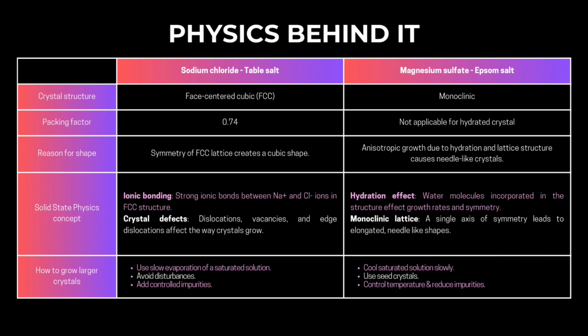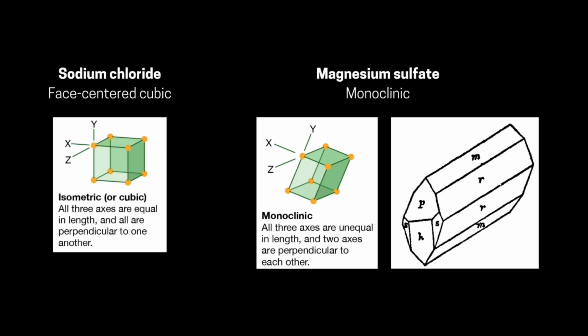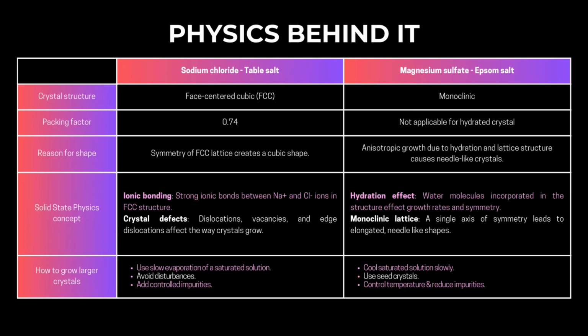Sodium chloride has a face-centered cubic crystal structure, and magnesium sulfate has a monoclinic crystal structure. This actually relates to the shape of the crystals. The face-centered cubic structure causes the sodium chloride crystals to form a cubic shape. For magnesium sulfate, the needle-like crystals are due to anisotropic growth caused by hydration and the lattice structure of the monoclinic system. Monoclinic crystals have only one axis of symmetry, with the other two axes having different lengths and angles.